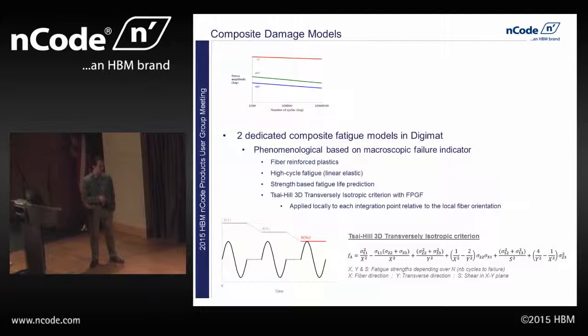So basically, we're going to use a failure indicator that was developed for unidirectional composites, and you can see it down here. And we're going to apply it in a way that makes sense for a short fiber-reinforced plastic. The way you can think about this is we're going to take this failure indicator, that includes the directionality of the material. You can see it's got these 3 different strength parameters here. And we're going to apply it on each individual fiber in the composite in the direction of the fiber.